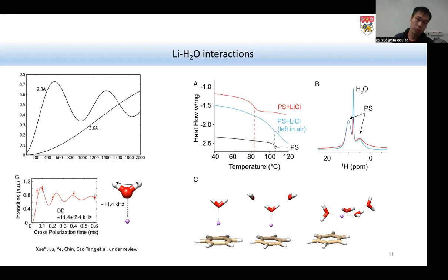DFT people made these simulations and proposed two possible modes for the lithium to water binding. If this interaction between water and lithium is driven by charge affinity, then the distance between lithium and a proton is approximately 2 angstroms. And if it is driven by an energy term called the cross exchange energy term between lithium and oxygen, then the distance between protons and lithium is approximately 3.6 angstroms. If we measure dipolar coupling, the difference in the curves will be, as we show here, very clear in solid state NMR.